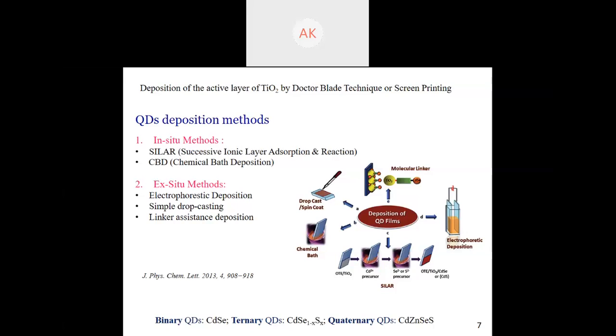So that is how you can also do it. Indium sulfide can also be grown by the SILAR method, but you may have better size control in CBD. There are literatures where they have compared methods: CdS can be grown by chemical bath deposition, CdS can be grown by SILAR, CdS can be made by the hot electron injection method and then deposited. Each method has its own advantages, its own size control, dimension control. So depending on your requirement, you can use them. I use SILAR in my lab. I find it user-friendly because it is just dipping into precursor solution. You can see the film forming right in front of you.